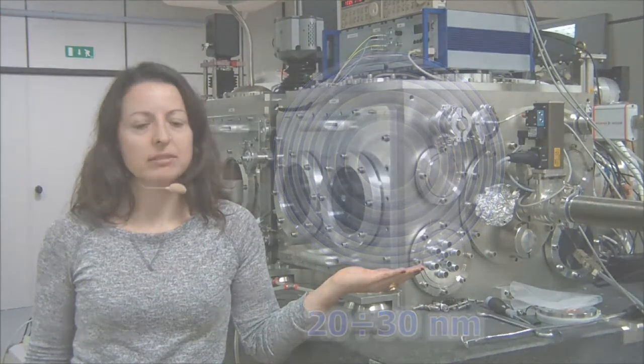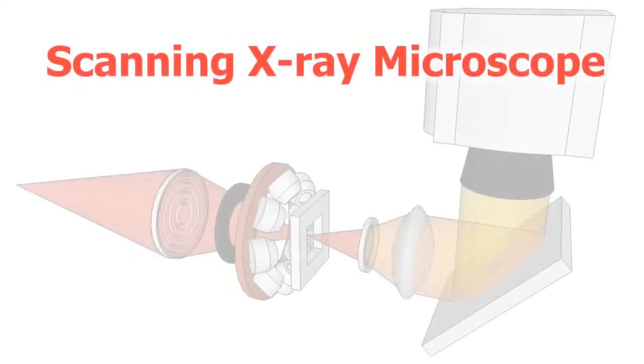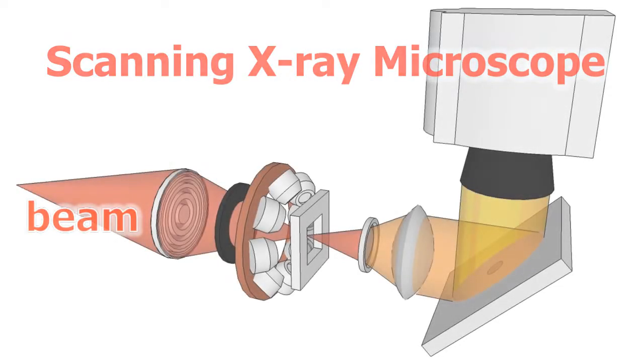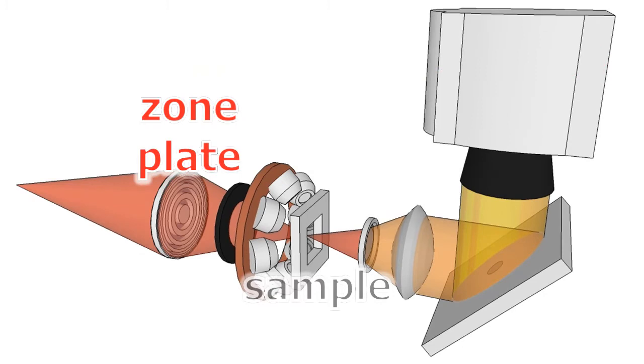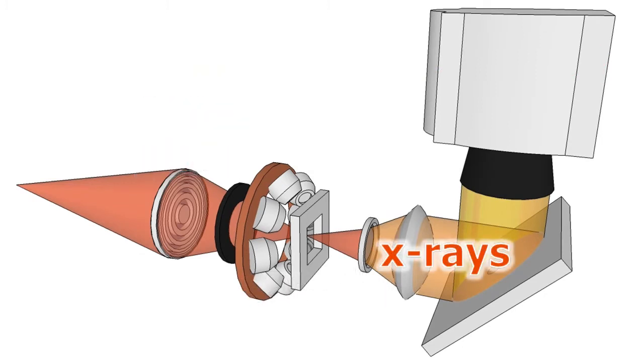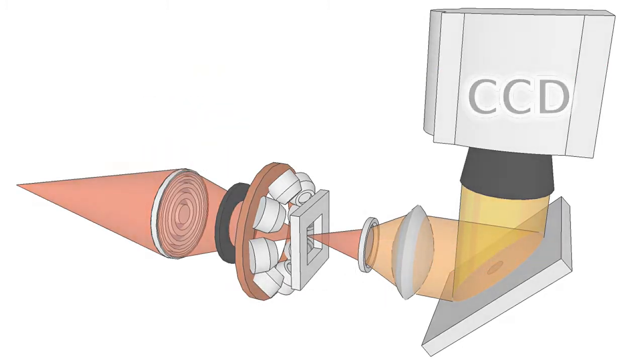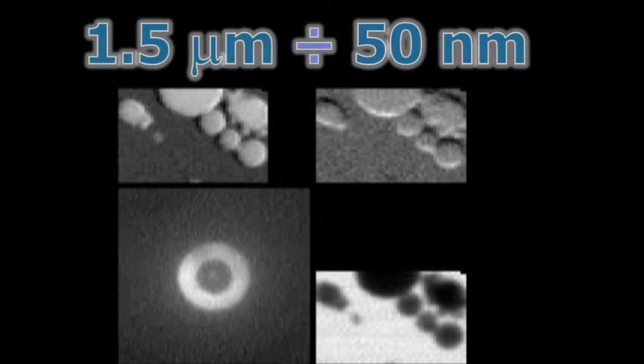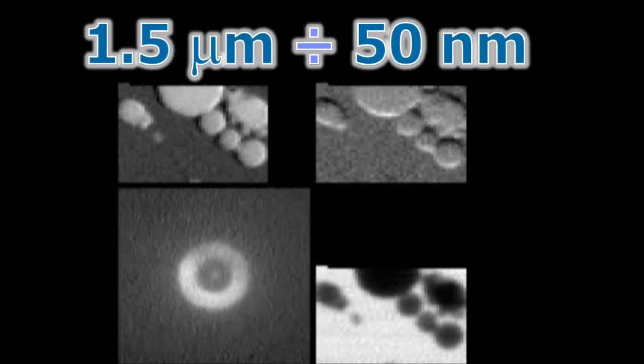In the scanning transmission mode, the beam is focused on the sample by another zone plate, and the transmitted X-rays are collected by a CCD, providing simultaneously absorption and phase contrast images. The spatial resolution can range from 1.5 micrometers to 50 nanometers.